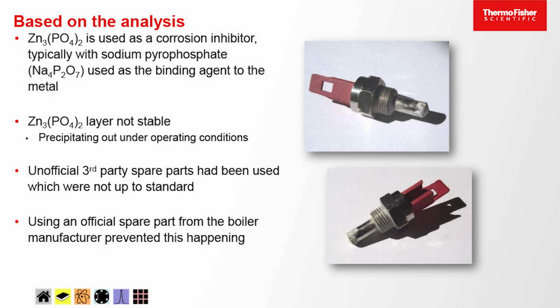So the zinc phosphate is usually used as a corrosion inhibitor. So the surface is coated with this zinc phosphate layer, and that's to stop the hot water attacking it while it's being used, with a sodium compound used as the binding agent. And unfortunately, this layer wasn't stable, and so it was precipitating out. It's not very soluble, and it does form a material that looks just like concrete when it comes out of the coating. And what they've been doing is not buying the parts for the boiler from the official supplier for the system. They'd be buying it from an unofficial third-party source.